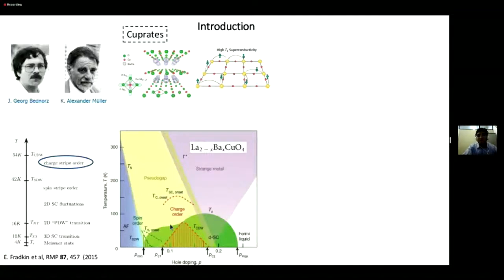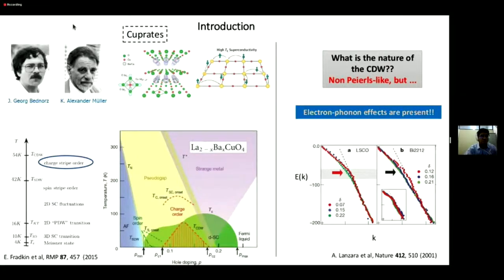So it's not due to electron-phonon interaction. Even though we know that the electron-phonon interaction plays one crucial role for this kind of compounds. For instance, here I present you one result that has been known for a long time: the dispersion of the electrons given by the ARPES measurements, the dispersion of the electron in cuprates, is directly affected by the electron-phonon coupling. Here, for instance, the arrows point out the exact phonon energy for the apical modes. So there is a coupling between the electron and the phonons that creates this kink here.